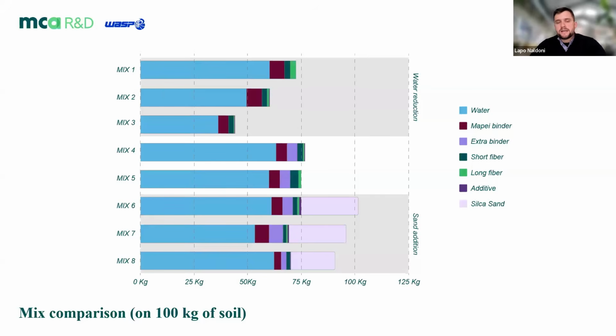In this slide, you can see the work that we have done together with Mapei, our partner for the materials, in order to arrive at a printable paste. At the beginning, we started together with WASP in order to reduce the amount of water inside the paste, in order to reduce the shrinkage of the material. But we understood quite fast that this material had a lot of problems in terms of adhesion, one layer with the other, and pumpability inside the machinery. So the pumpability was not perfect, with a lot of abrasion inside the pump due to the stiffness of the material.